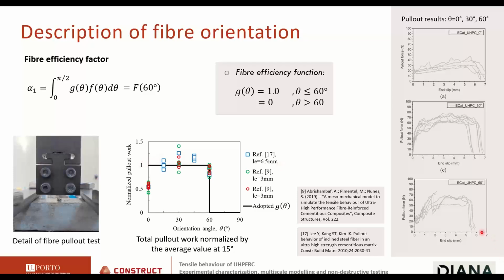Well, one variable that can describe this is the pull-out work. Okay, so this is the normalized pull-out work of many tests. This is the total pull-out work. It would be better to determine this pull-out work for small displacements only, but in any case, it does the job here. So you see that it could be better to use some function a little bit more complicated.